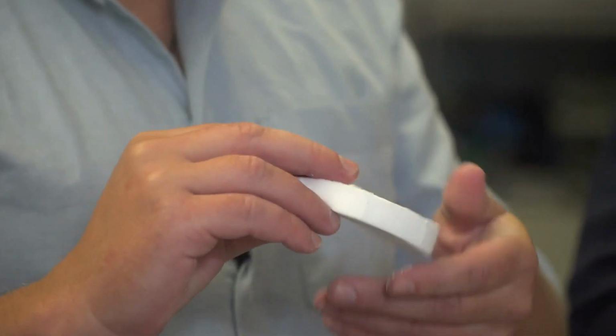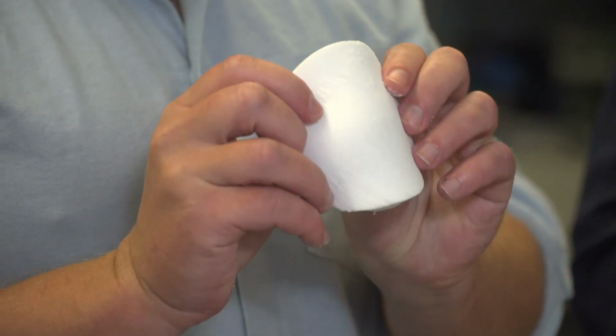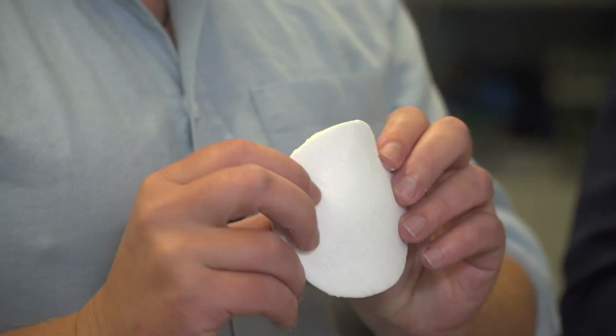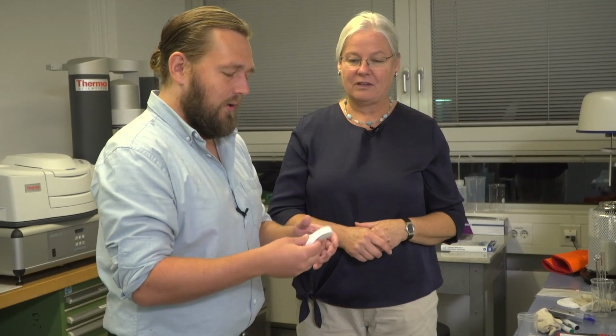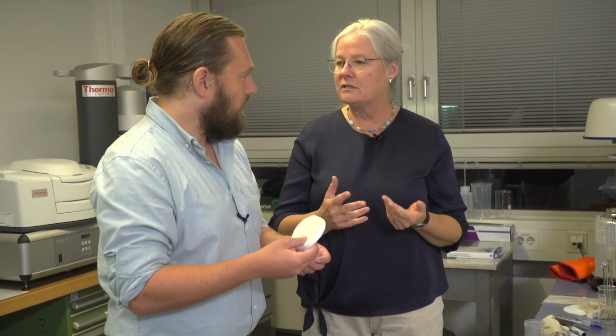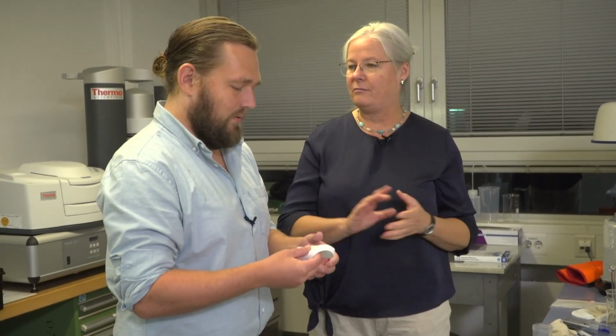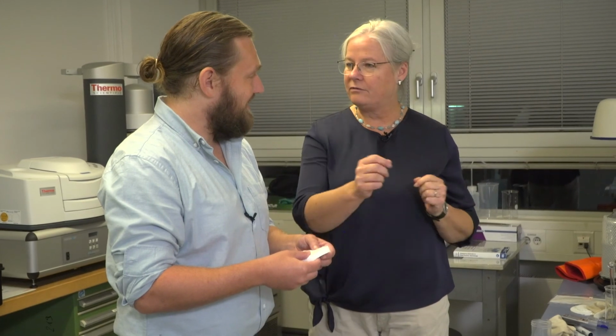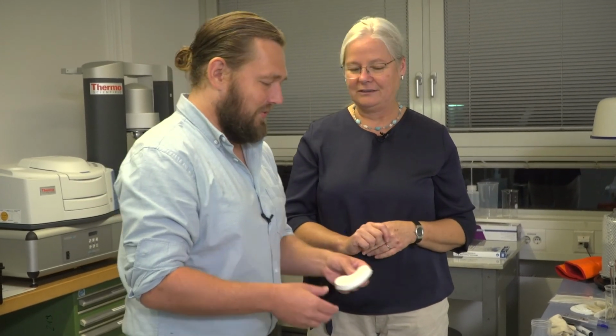And so this is all from the specialty silanes. It's an organically modified silica aerogel with no fiber reinforcement. Wow. We do a lot of changes with this material, and with fibers, we tested a lot of them. Short fibers, felts, and so on. All the permutations. Very good.